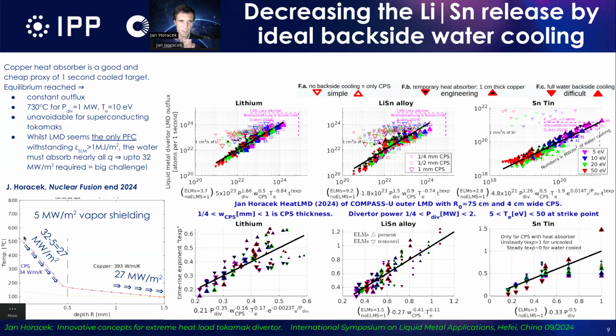And this is in fact explained here. So you get the temperature profile where on the surface for lithium tin alloy, I think it's the case, I get about 550 centigrades. Then the thermal gradient below the surface gives me that there is about 27 megawatt per square meter flowing to the backside of this target, where I assume that I have 0.5 millimeter capillary pore structure and then 1 millimeter the copper. And at the backside of the copper, I have some perfect cooling. The perfect cooling keeps the temperature constant at 100 centigrades, but it has to remove, in such a case, 27 megawatt per square meter, because only 5 is lost by vapor shielding on the surface.